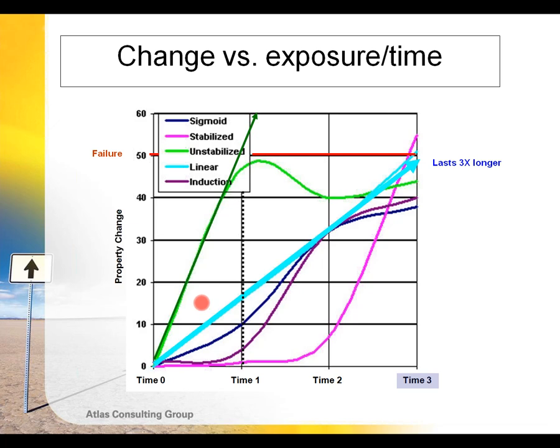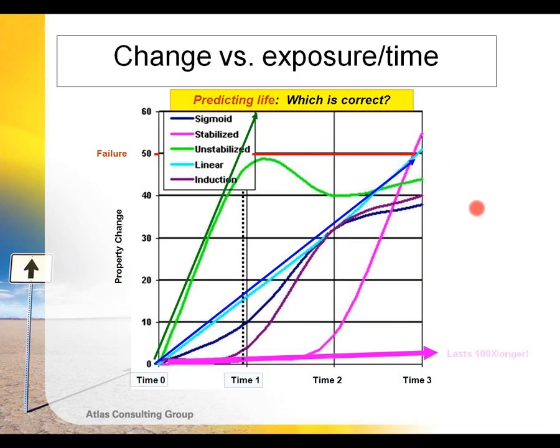On the other hand, if we run it out to time interval number three out here at the end, we may say, aha, the actual property change leveled out at this point, just beyond our last measurement, and actually had very, very little property change after that. And so it actually may have been a very acceptable product, but I stopped my test too soon, and I didn't understand the shape of the degradation curve versus exposure or time.